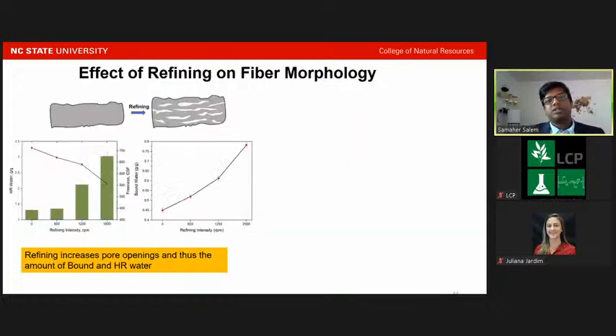We also measured how the refining is affecting the fiber morphology. And we could see that with the increase of refining, the freeness decreases and the hard to remove water and the bound water increase. The increase in the hard to remove water and the bound water is due to opening up of the macroscopic spaces in the lamellar structure of the fiber cell wall.